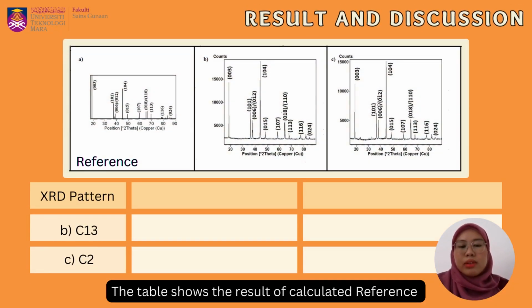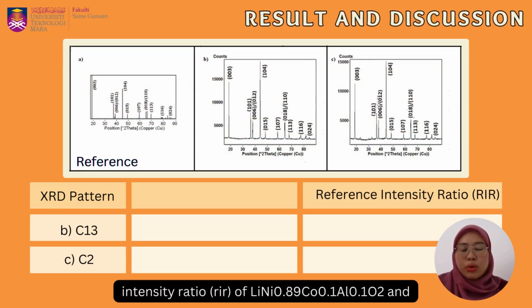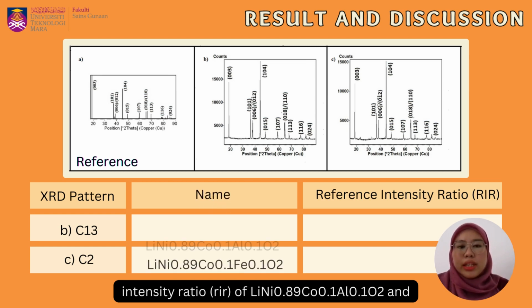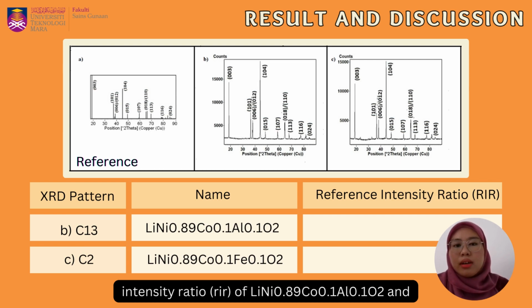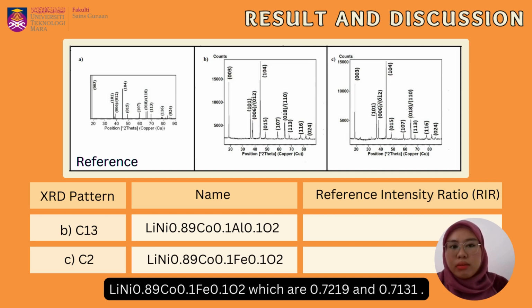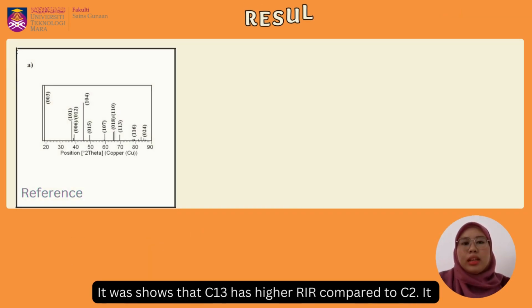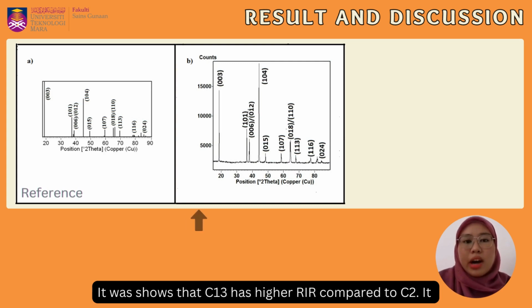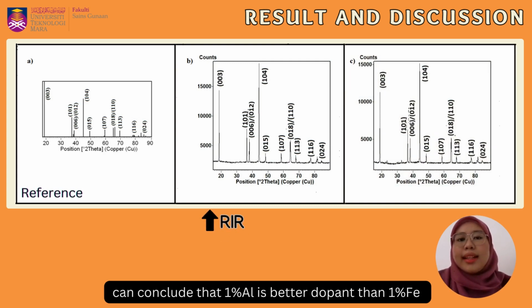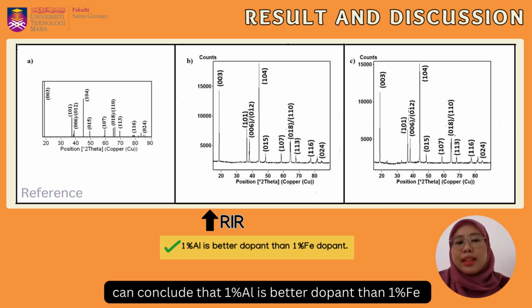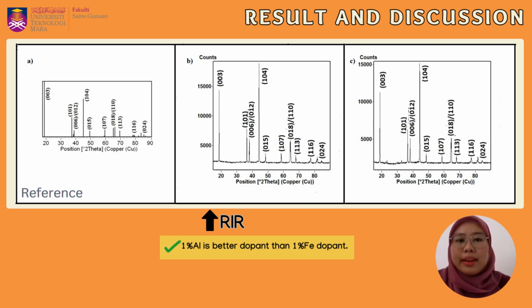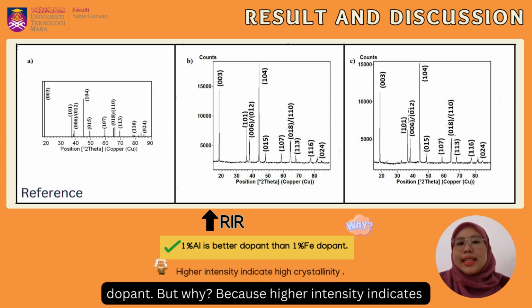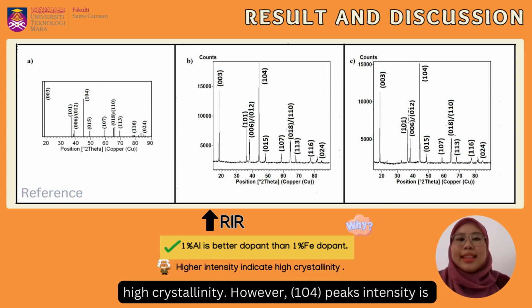The table shows the result of the calculated reference intensity ratio (RIR) of nickel-rich lithium nickel cobalt aluminum oxide and lithium nickel cobalt iron oxide, which are 0.7219 and 0.7131 respectively. It was shown that C13 has a higher RIR compared to C2. It can be concluded that 1% aluminium is a better dopant than 1% iron dopant. But why? Because higher intensity indicates high crystallinity.